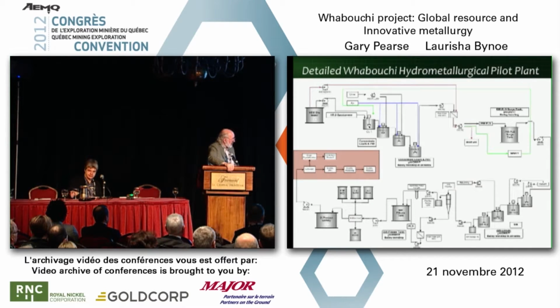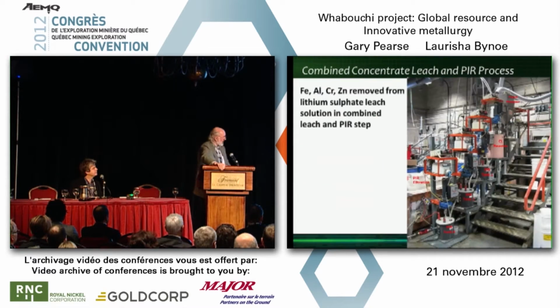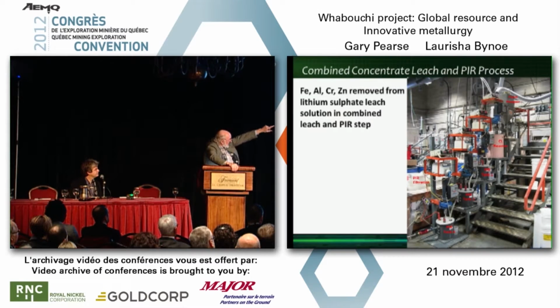And once we have put it through that process, we then go to the IX, ion exchange process, in which we pass the material through and end up with a very pure lithium sulfate solution. And this is where the innovative part of the process occurs. And we'll go through that through a little more attractive diagrams here. This looks almost like some kind of rocket science here. This is the primary leach, and the primary purification cascades down through these tanks here.